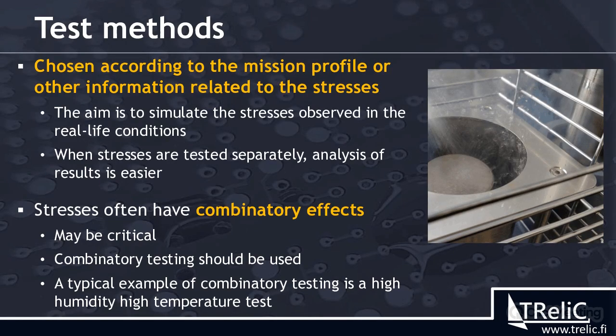However, the problem is that from time to time, we have combinatory effects of the stresses, meaning that we have two stresses which accelerate each other, make them more critical. And this can be an issue. So it's always important to also consider whether this could be possible, and is it important to test also these different combinations. For example, high humidity, high temperature test is probably one of the most used tests in electronics because of this, because it has been seen that this is very important combination.